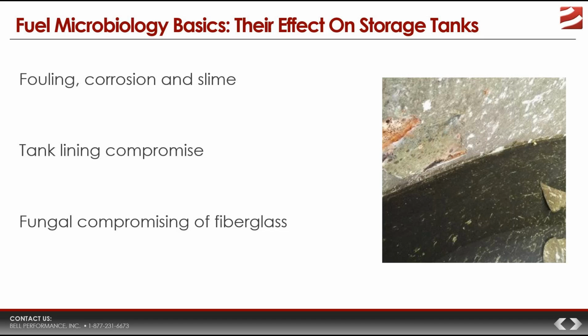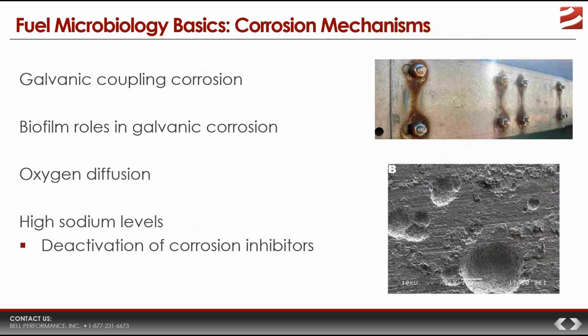Now, anytime you have metal surfaces and metallic components in storage tanks, you're going to have corrosion mechanisms at play, damaging the tank. Well, what are these corrosion mechanisms? With corrosion, the most prevalent mechanism for observed tank corrosion in the wetted area, we're talking about corrosion under the fuel line, as opposed to vapor space corrosion, so we're talking about wetted corrosion, is when you have the formation of a galvanic couple between the steel or the metal in the tank and something like iron sulfide ions that have been produced by microbes.